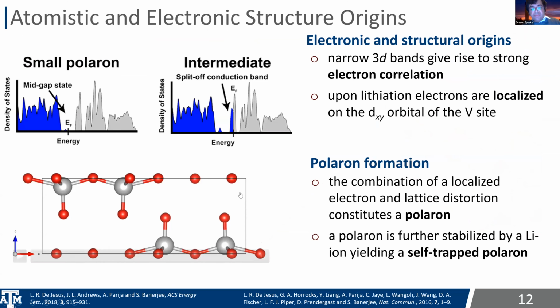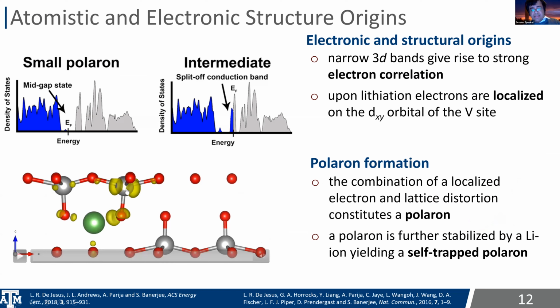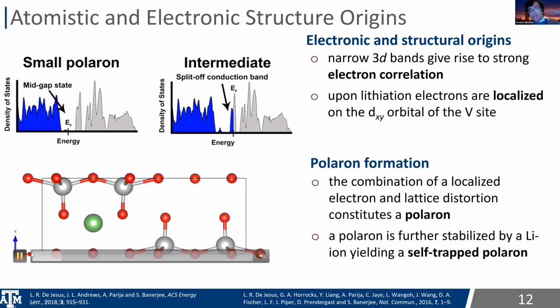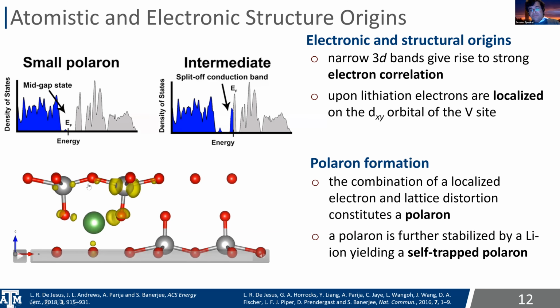And then something we've spent a lot of time looking at is the coupling of the localized electron in this dxy state with the lattice, which then induces this distortion, as you can see here in the simulation. And there's plenty of experimental evidence for the formation of this local lattice distortion, which is essentially a small polaron. Okay, and then the small polaron can interact with the lithium ion and give you a self-trapped polaron, and the self-trapped polaron can find it quite difficult to diffuse through this V2O5 crystalline lattice.